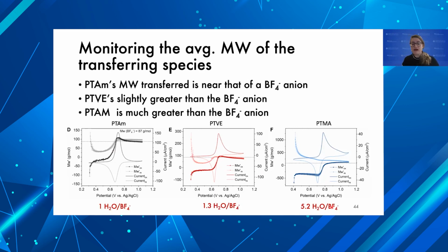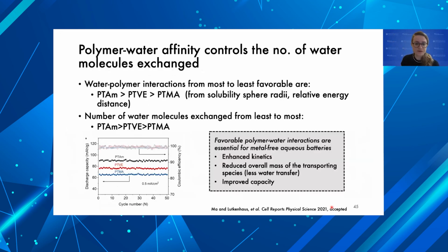But PTMA, which has the worst water interactions, drags in a lot more water. And that's explaining why there's such sluggish kinetics and why the hysteresis is so poor, because you're transporting a lot more physical mass in and out of the electrode. That manifests in really big changes in the discharge capacity.